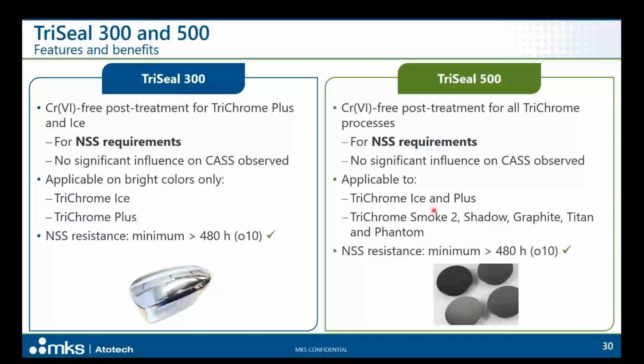Again, the requirement is focused on neutral spray corrosion resistance, so no significant influence on CASS you will get from this. And the performance of this post-treatment is good with all the trivalent chromium processes, being bright or being dark. In this case, we can also achieve more than 480 hours in the neutral spray test.